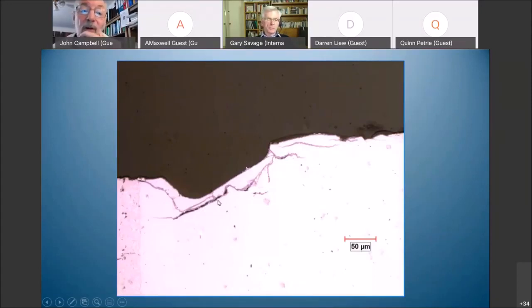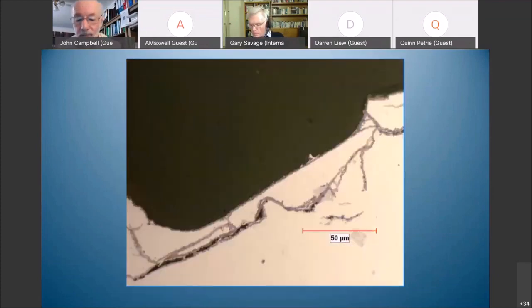And what's more, they're parallel. These are pretty well parallel. And this is a hallmark, a distinguishing feature of bifilms. You remember them growing because of the way the dendrites move. And so as the dendrites progress, they straighten the bifilms between them. And this is an instance where we have, oh yes, here's a better view, where we have a single grain here, and bifilms must have grown in this direction. And so here we have our bifilms flattened out in